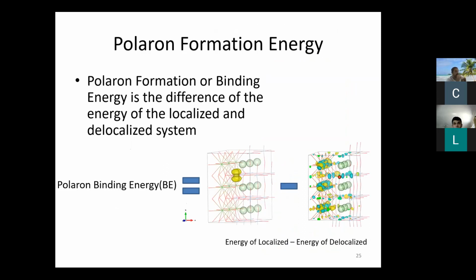This is the supercell system of the LLTO that I run. In order to get the polaron binding energy, we want to ask: what's the energy of the delocalized system, and what's the energy of the localized system? The yellow right here is the charge localization in terms of spin. Right here, you can see it's delocalized across the whole system. The blue is spin down, yellow is spin up. So in this system, it's all a spin up system.